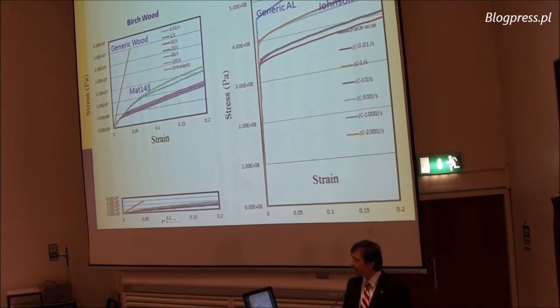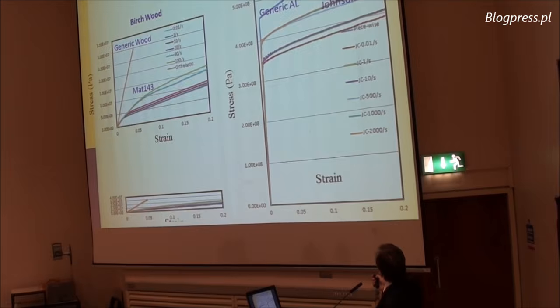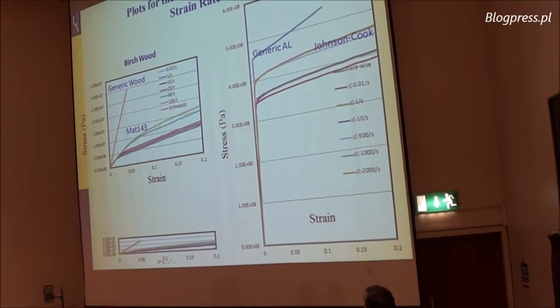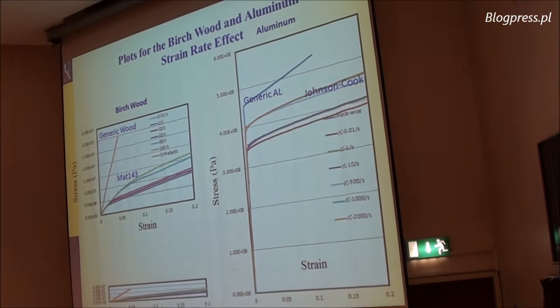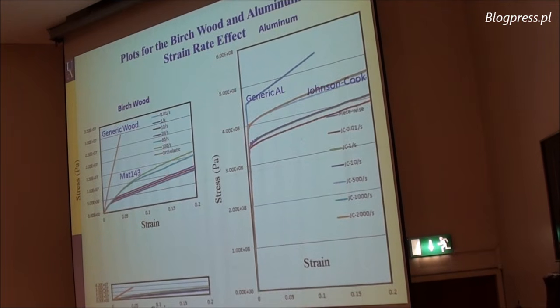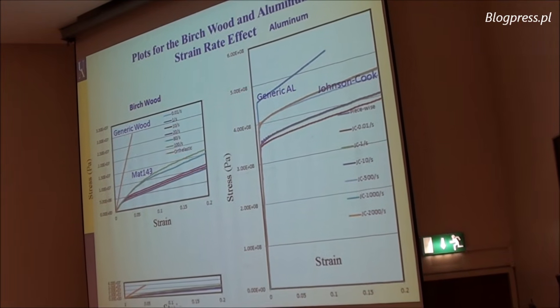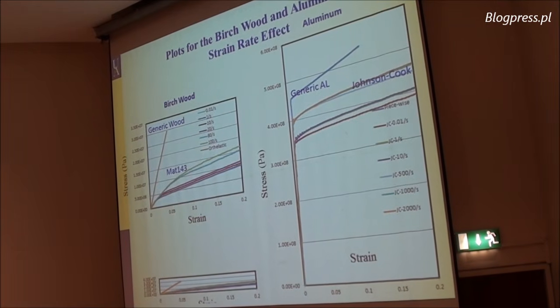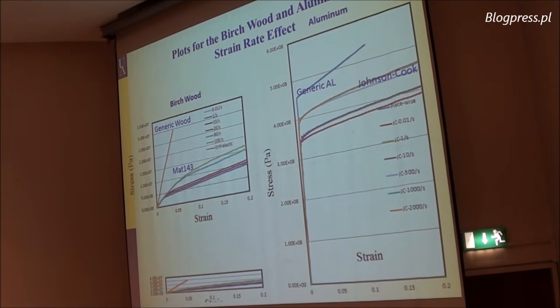Again, if you look into the stress-strain curves of the different models that we use, like Johnson-Cook or bilinear, or this tabulated, together with the material model used for the wood, the generic orthotropic model or material 143, and you squash this to this level to show the same vertical scale, you can see how weak the tree is in comparison with aluminum.